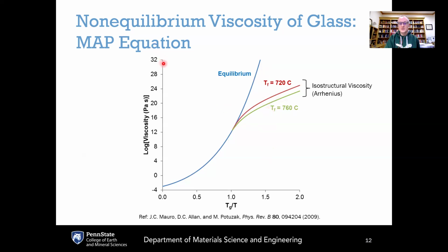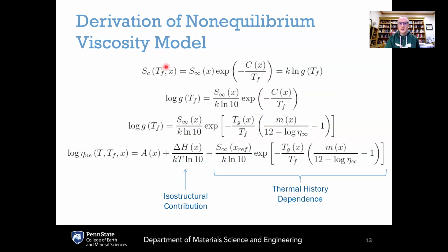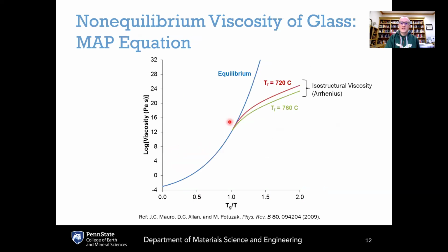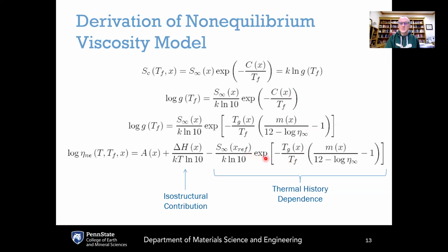Now, this MAP model actually has two parts to it. I'm not going to go through this whole derivation here, but I'll just point out that there's two parts. This first part shows the isostructural contribution, and this shows the Arrhenius dependence with respect to temperature if you have a fixed fictive temperature. So this term here is what gives you the Arrhenius scaling of viscosity in the isostructural regime. The other term depends only on the fictive temperature TF and not on the temperature T. And this is what gives the thermal history dependence of the viscosity.